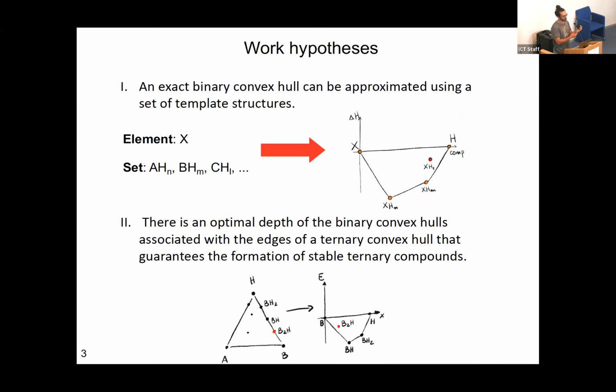So in our work, we tested two hypotheses. The first is that to obtain a real convex hull, we can approximate it with a convex hull obtained by a set of templates or prototype structures. And the second is that there is a correlation between the depths of the binary convex hull associated to the edges of a ternary convex hull that guarantees the presence of ternary stable compounds. If you want to know more, come to the poster session tomorrow.